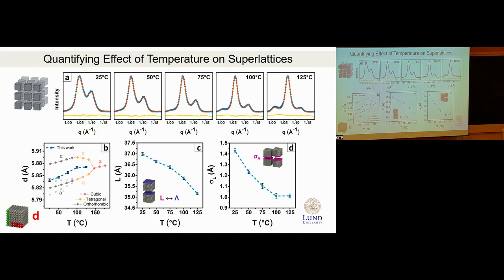Just in your tetragonal region, you still have the orthorhombic line. I'm not quite sure what's going on there. The way we compare with the literature is that from our model we only obtain one lattice parameter, and we don't know which one it is, a, b, or c. So we calculate sort of an average cubic-like constant, which we then plot. These values, a and c for the tetragonal, orthorhombic, and cubic, are taken from the Kanatzidis work on single crystal cesium lead bromide, where the structure is unambiguous and fully resolved as a function of temperature.